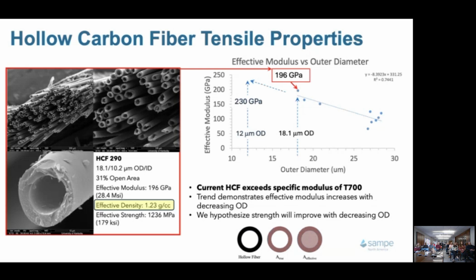The big point is that the effective density is now down at about 1.23 relative to about 1.8. That's a big drop in density, which I really can't underscore enough, because if you weren't concerned about density, you could argue you'd just use glass fiber, make a thicker part, and spend a lot less money than going for a carbon fiber part. It's all about lower weight in the part.